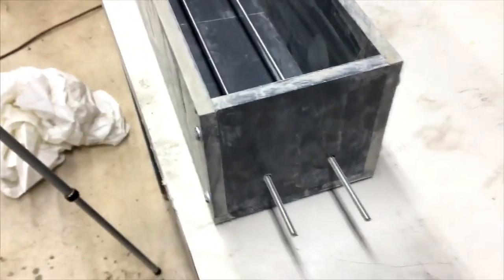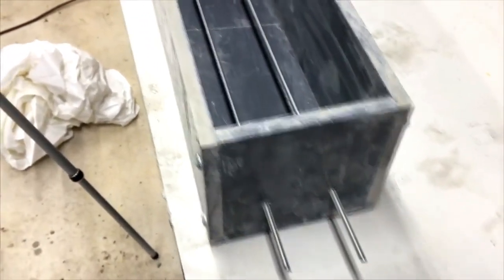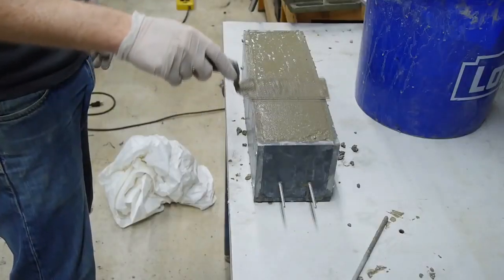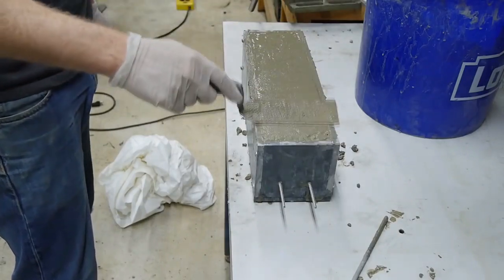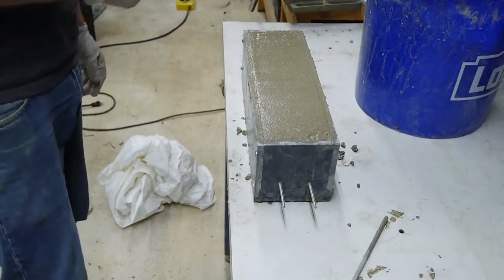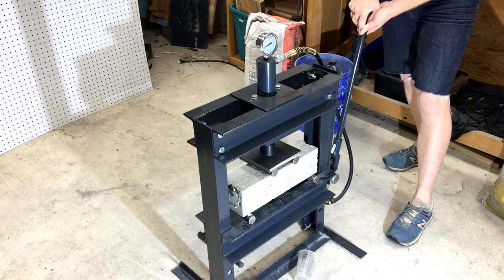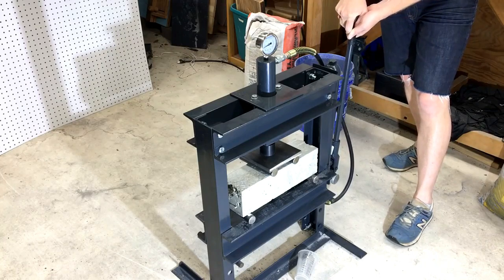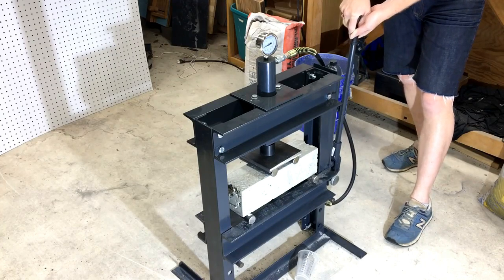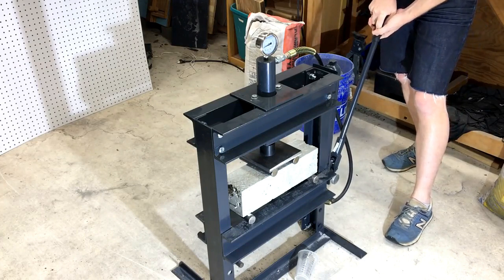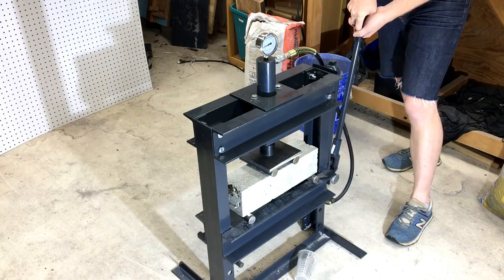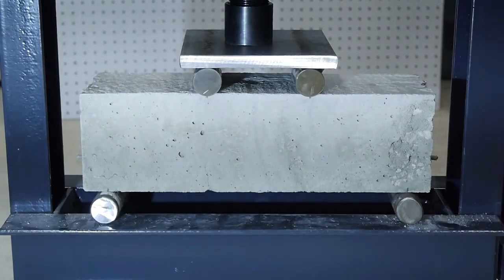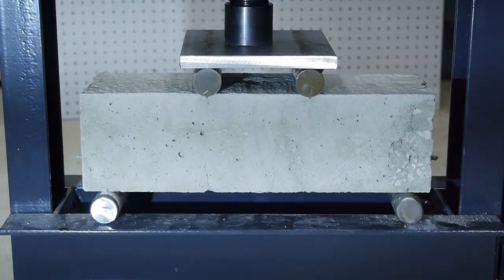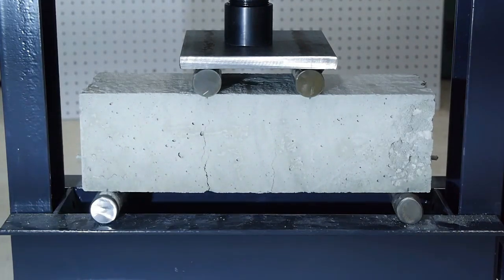I made a new beam with a couple of steel threaded rods cast into the lower portion of the concrete. These threads should act just like the deformed ridges in normal rebar to create some grip between the concrete and steel. Under the press, the first thing you notice is that this beam is much stronger than the previous one. We're already well above the force that failed the unreinforced sample. But the second thing you notice is that the failure happens a little bit slower. You can easily see the crack forming and propagating before the beam fails.